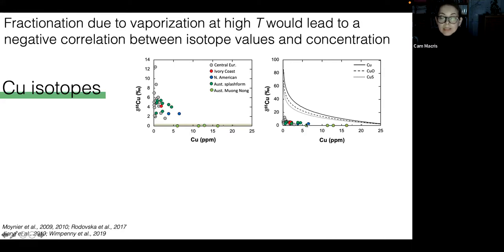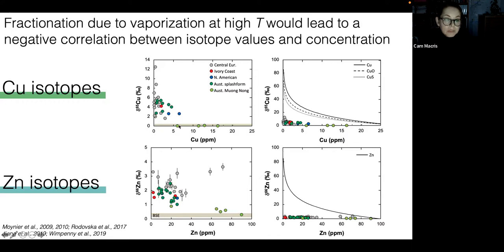The plot on the right is the same data, but the y-axis scale has changed. I've added curves representing the theoretical predictions of fractionation according to Rayleigh evaporation models for pure copper, copper oxide, and copper sulfide, which you can see do not explain the tektite data. We can look at the same relationships for zinc here and see that there is also a general trend of increasing delta 66 zinc with decreasing zinc concentrations. And again, a theoretical Rayleigh fractionation curve for zinc evaporation does not explain the tektite data.